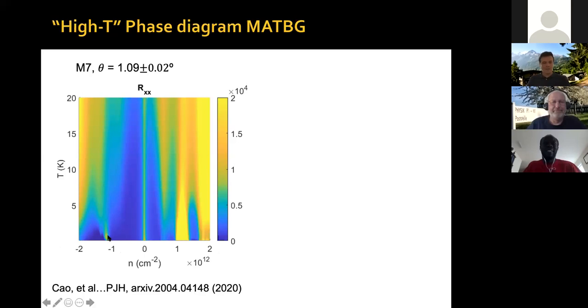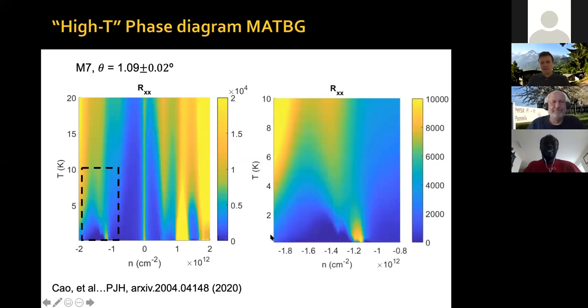There is a superconducting dome. Let me focus a bit on this region. But this is, by any standard, a very high quality transport device, with lots of correlated states and superconductivity. If I zoom in on this region a little bit, you see that this is our correlated insulating state that happens at low temperatures, at 2 holes per moiré unit cell.